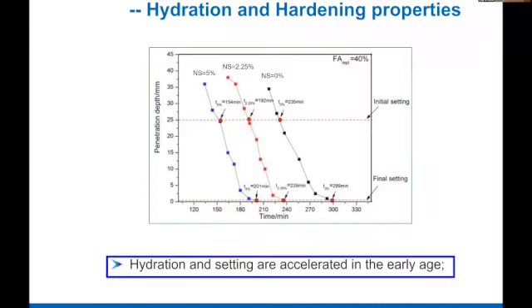One of them is when you use large quantity of pozzolanic material such as fly ash, which is obviously desirable as far as sustainability, but when you use large quantity of fly ash, the reaction slows down. And this is very important in construction where you want a fast response. So this is one of the drawbacks when you use large quantity of fly ash. So here, for example, cement is replaced with 40% fly ash, and we are measuring the reaction with the Vicat needle test, and you can see the initial set and final set.